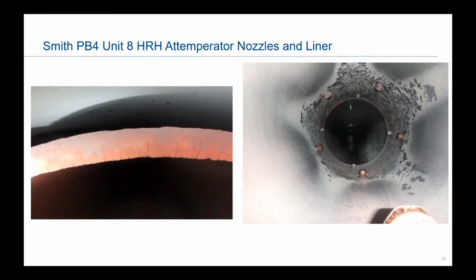So a lot of hours on those nozzles. We did remove the initial set of nozzles in the fall of 2019 after about 6 months of operation. And we visually inspected them. Really didn't see any significant erosion at all or any changes in that nozzle. And then we sent them off to Fisher, and they did some further X-ray examinations and some destructive testing. And Justin could probably speak to their results better than I could.